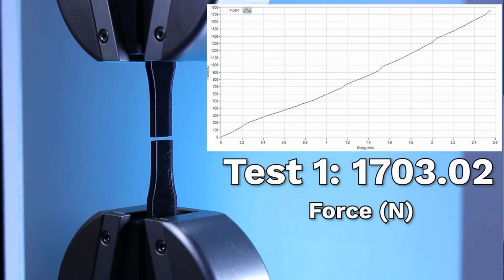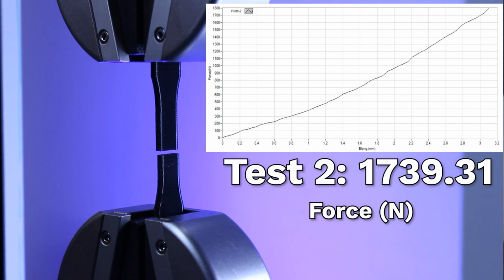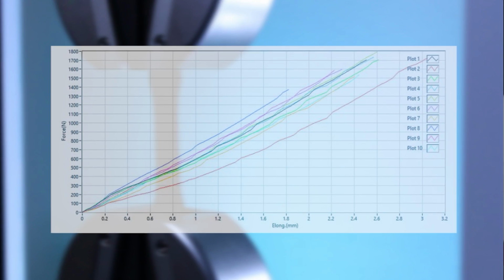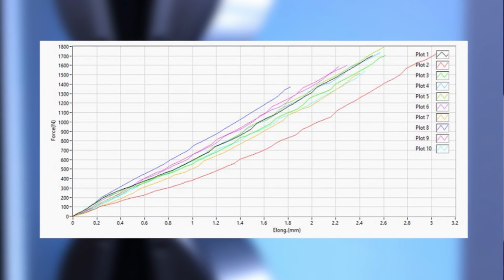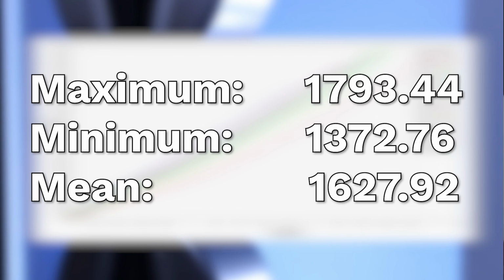So let's go ahead and start with Tangled PLA because it's the control group. So let's just do a quick refresher of what it's able to take. After popping Tangled 10 times, we get an average peak force that it's able to maintain of 1,627 newtons, which is about 250 pounds or so, which is really impressive for a dog bone to hold up. I mean, to have a whole guy hanging from this thing is pretty darn good for PLA, which is pretty darn brittle. That comes out to an average stress of about 31.3 megapascals, which is where we expect it to be. And that's based off of all of our previous tests and has continued to hang around there.